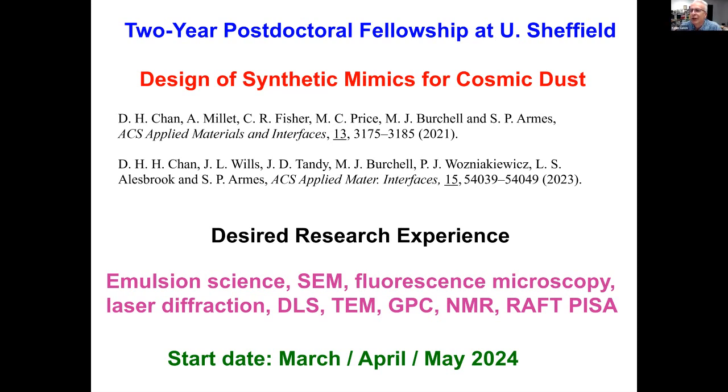I'm not sure. Sebastian is online and could probably comment on how he's generating them. One thing I should say is we're currently designing some cationic nanoparticles to be antimicrobial nanoparticles. In that case, we find they're only antimicrobial when we introduce some hydrophobic character as well. Those cationic mixed hydrophobic nanoparticles do stabilize foams quite nicely after handshaking, so I think those would be prime candidates for stabilization of nanobubbles.